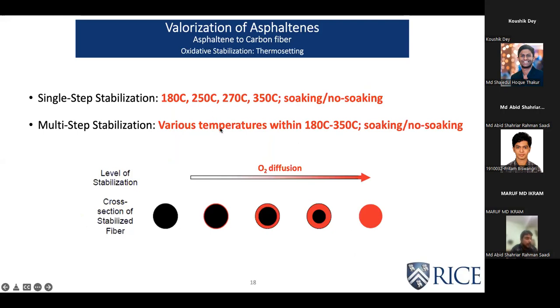After the green fibers were formed, the next step, if you remember, was stabilization. Here we tried different types of stabilization routes, single step and multi-step stabilization. One thing to remember is that during stabilization we are doing oxidation, and oxygen diffuses from the surface towards the inner core of the fibers. The more oxygen diffuses, it goes from the outside radially towards the core. So you need to make sure that you have the proper fiber diameter and other parameters during this stabilization step, so that the whole fiber is oxidized.